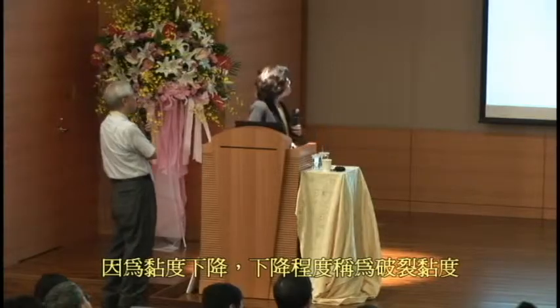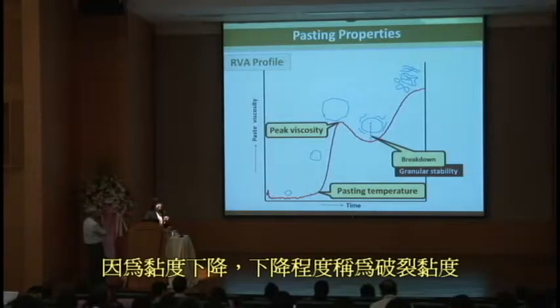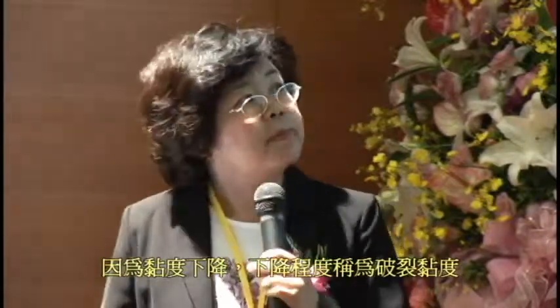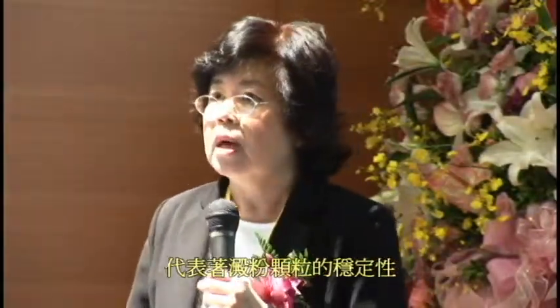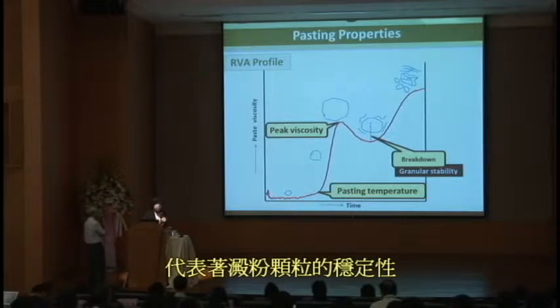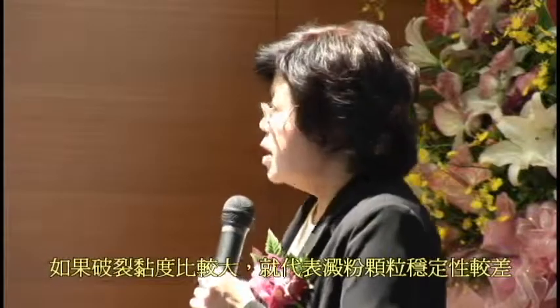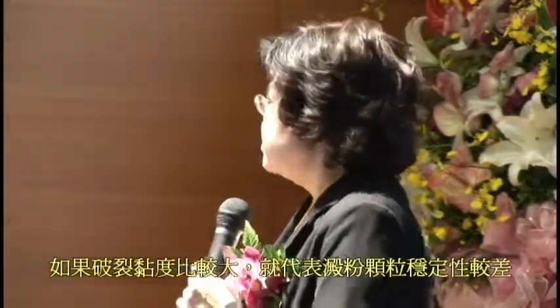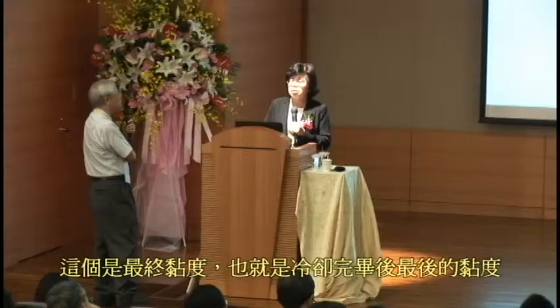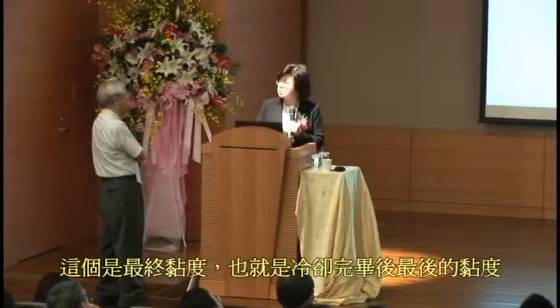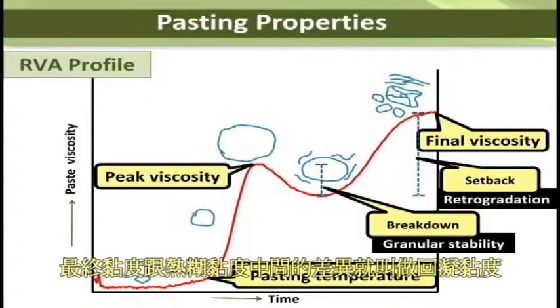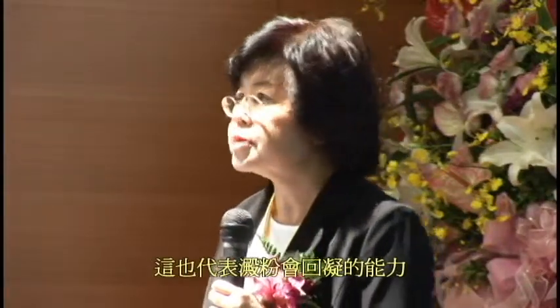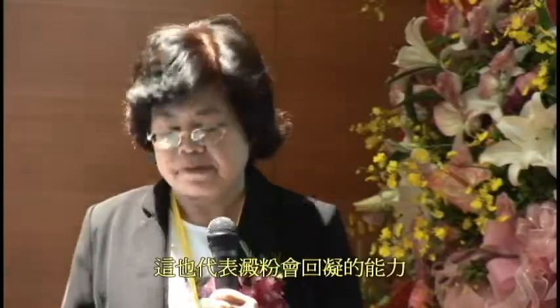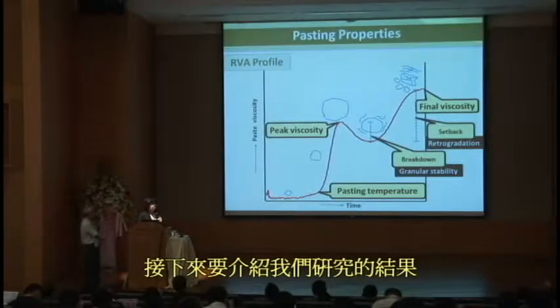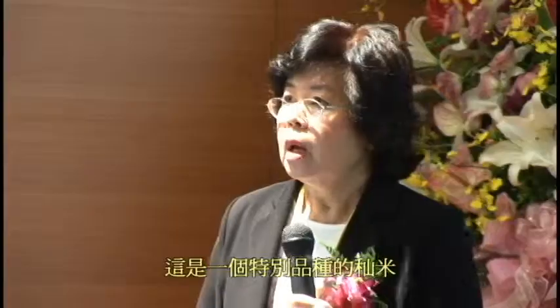After that, there is a drop in the viscosity, and the difference, the drop of the viscosity, is called breakdown. This breakdown indicates the granular stability. High breakdown means that the granule has less stability. The final viscosity is the viscosity after cooling. And the increase of the viscosity during cooling is the setback, which indicates the extent of the retrogradation of the flour. Okay, so now we come to the results of our study.